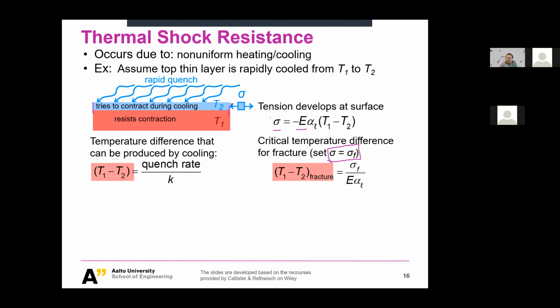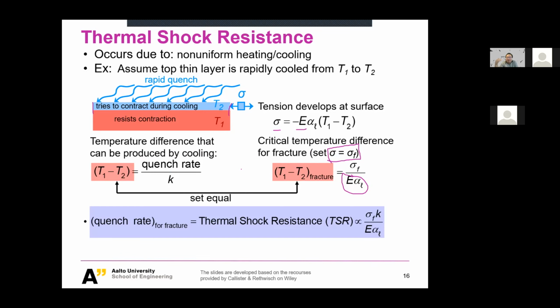So if we just take the sigma F into this equation right here, you would derive a limit delta T. So when the T1 minus T2 reaches this value, the sigma F divided by, because these two are constants, right? Material constants. Divided by this value, we will trigger fracture for the material. And T1 minus T2 is related to quenching rate. So finally, the failure of the surface material is related to quenching rate, right? That's why we have the so-called limit quenching rate or thermal shock resistance, meaning we cannot apply an extreme quenching rate to our materials, because if this quenching rate is too high, it will trigger a fracture. This fracture is caused not by mechanical loading, but by thermal loading, by thermal stresses.